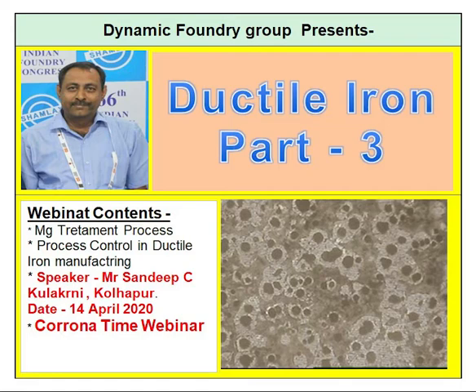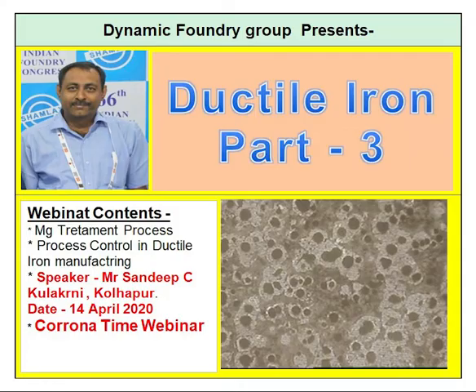Pouring time should be around six to seven minutes depending on your treatment size and pouring practices. Another process control point is the ladle cover — to reduce magnesium loss and temperature loss. Both magnesium loss and temperature loss will be controlled.